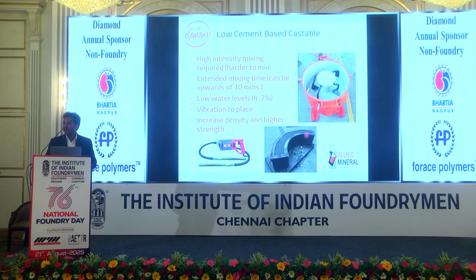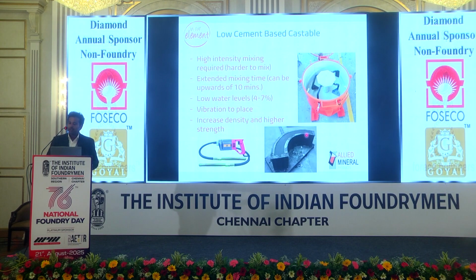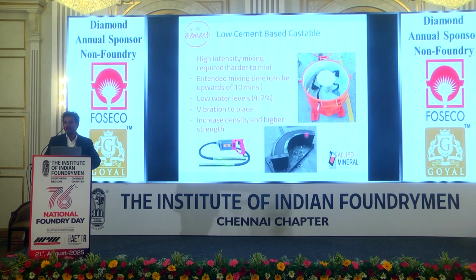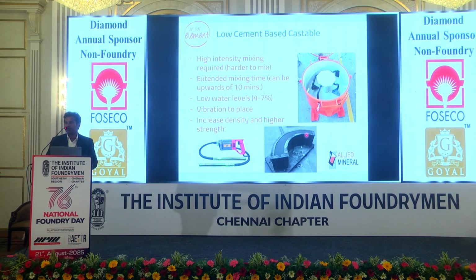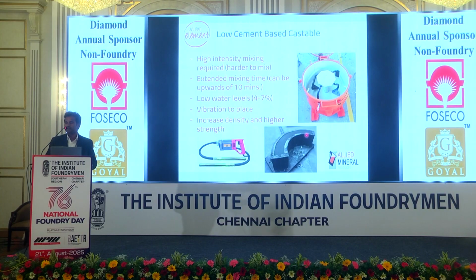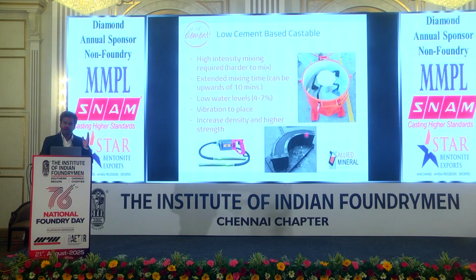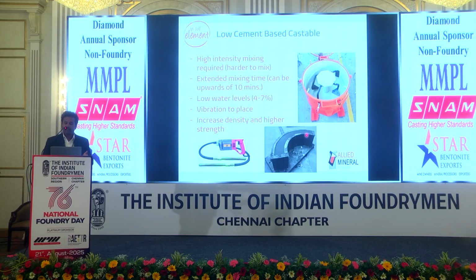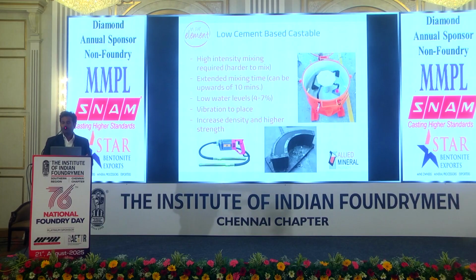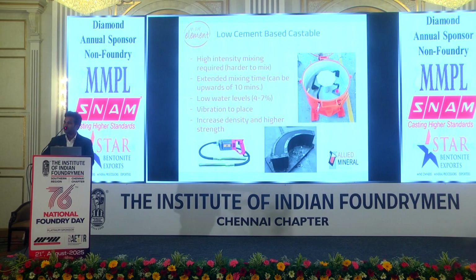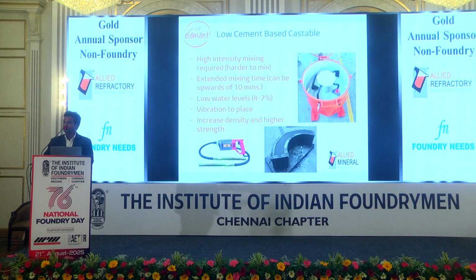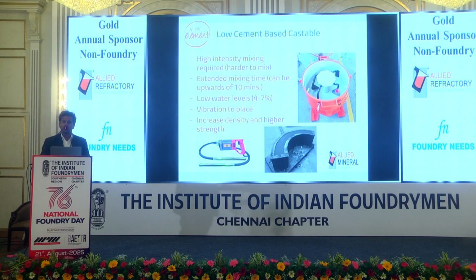Even though it requires some specialized equipment like a pan mixer and needle vibrator, the product has to be installed in the way it has been designed. Certain products are designed only for a vibration cast. If designed only for a vibration cast, it has to be used with a pencil or needle vibrator. Compared to the high cement refractories, low cement refractories need a shear force to mix properly. That's the reason we always recommend going with a pan mixer.